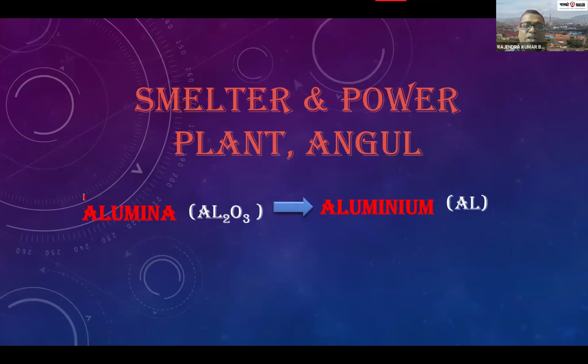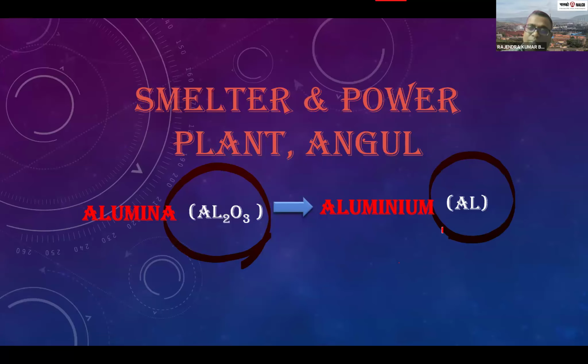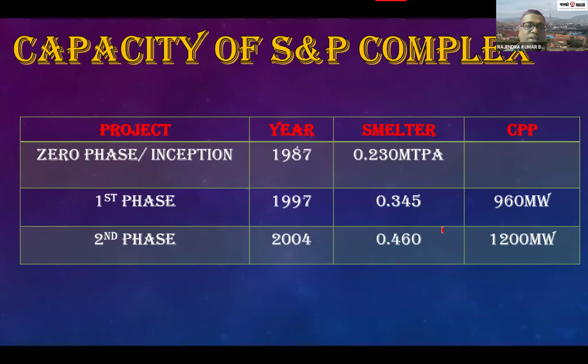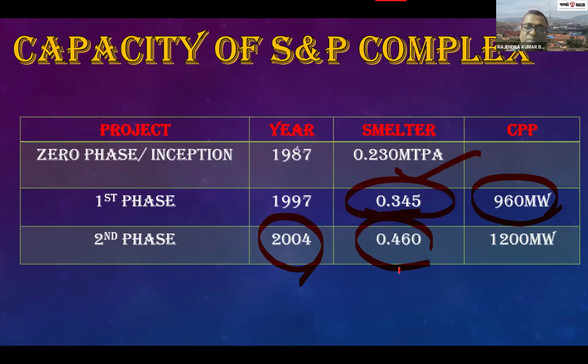Again, we are going to the smelter and power plant, where we are processing the alumina to aluminium. That's the Al2O3, and we use the electrolysis process to get aluminium. In the zero phase, since the inception in 1987, the capacity was 0.23 million ton per annum. In the first phase expansion, 1997, we added to make 0.35 million ton per annum, with captive power plant capacity of 960 megawatt. Second phase expansion in 2004 is 0.46 million ton per annum smelter, and this has 1200 megawatt capacity.